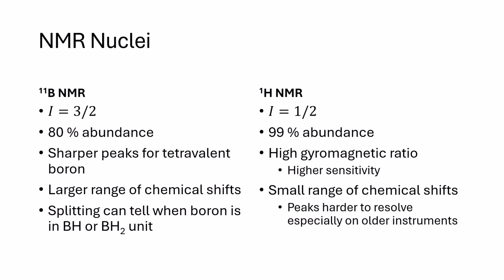Subsequently, the other type of nucleus used is the proton, which has spin 1/2 and is very highly abundant. It also has a high gyromagnetic ratio of roughly 3 times that of boron-11, leading to a higher sensitivity. However, it does have a small range of chemical shifts, and especially in older instruments with a weaker magnet, it can make the peaks hard to resolve.